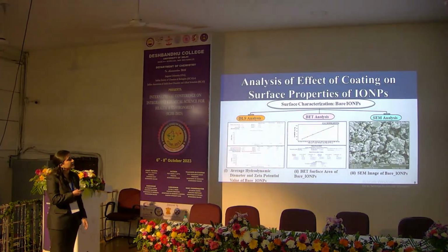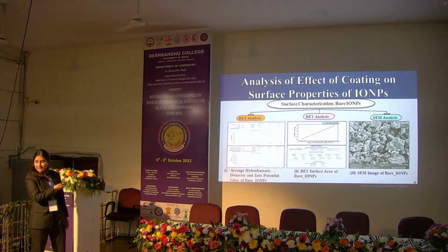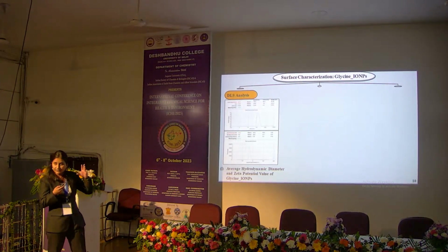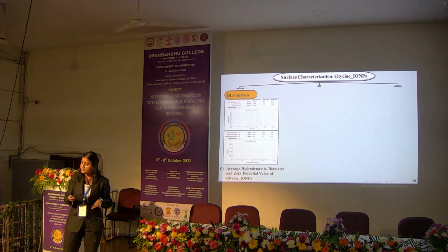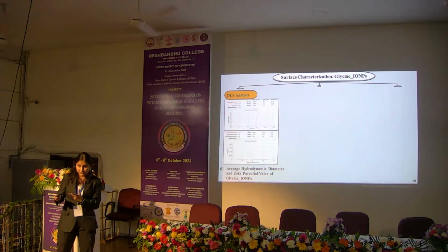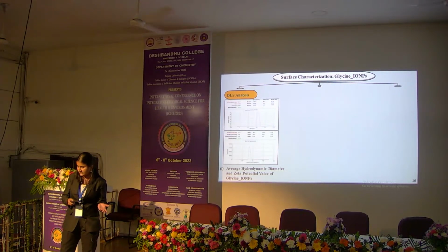Next, for the analysis of the effect of coating material on the surface properties, we have performed DLS, BET and SEM analysis, and from the DLS analysis, it was observed that the hydrodynamic diameter of the amino acid coated formulations was higher than that of bare iron oxide nanoparticles.